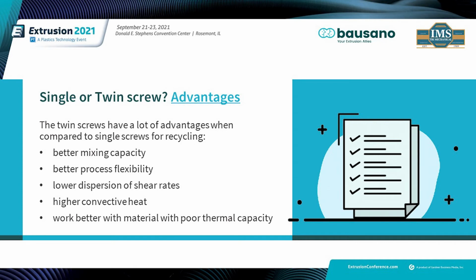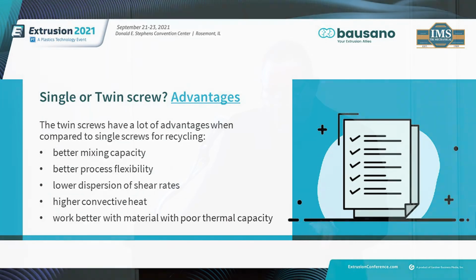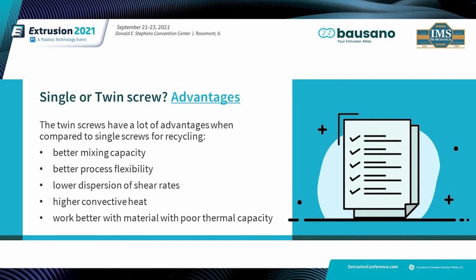Twin screws can process multiple functions in series, such as melting, mixing, venting, and cooling, all in one extruder. The process parameters like time distribution, lower dispersion of shear rates, or higher convective heat transfer can be better adjusted in twin screws. Single screw extruders exhibit relatively low dispersion and devolatilization outputs. Depending upon the available raw material, this can lead to inadequate compound quality. So in the end, the best solution lies in using a twin screw extruder for compounding and recycling, except in the case where you have ultra high contamination and you've got a conjunction of two technologies.